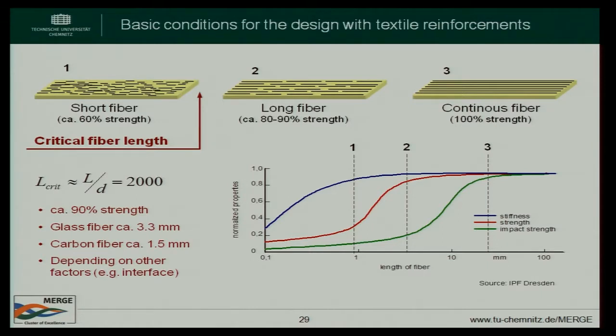and which fiber length you need. It's easier to make a thermoplastic process with short fibers instead of endless fibers. So you have to look at whether it is necessary to use endless fibers, long fibers, or maybe it's already sufficient to use short fibers. Because in a part, you can see it here, your properties of course depend on your fiber volume content, but also on your fiber length.